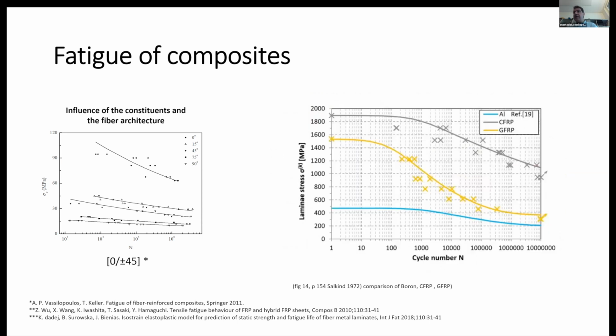And if we compare, here is a comparison between aluminum, which is the blue, and then GFRP and CFRP. You see again the huge difference between the properties. This comes to confirm what we said before, that composites perform much better than the other materials at a lower density. And this is why when we talk about composites, probably you have already discussed this, we talk about the specific properties of the materials and not the absolute properties, where specific property is the property divided by the density of the material.